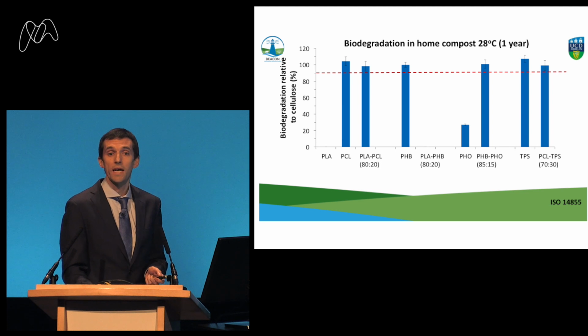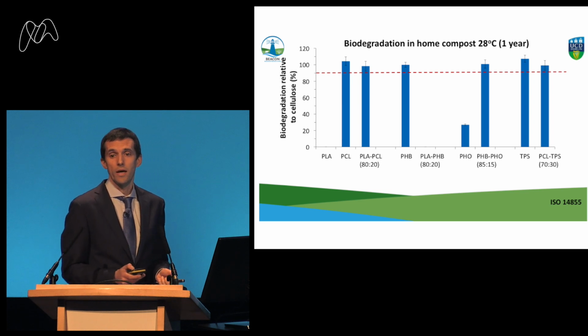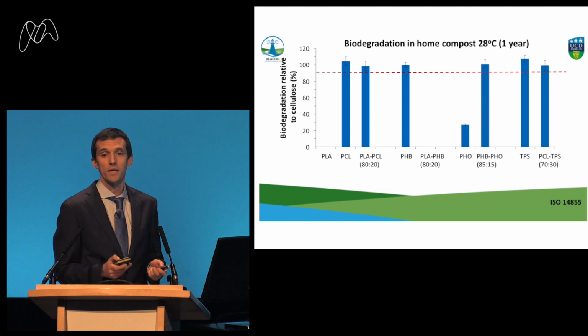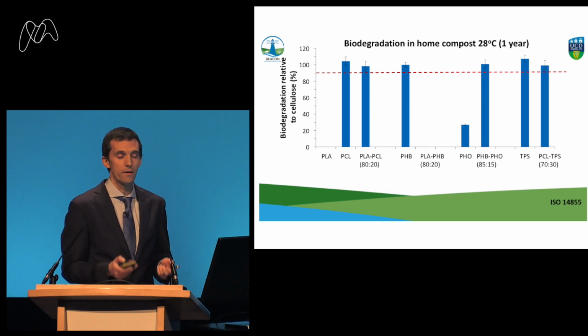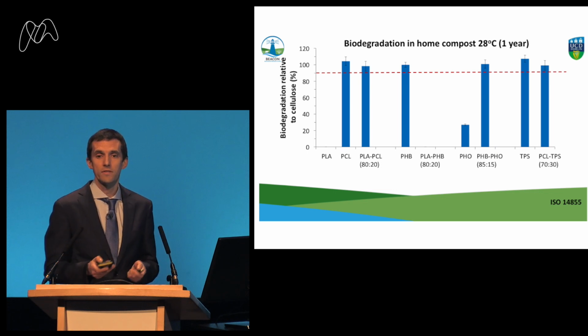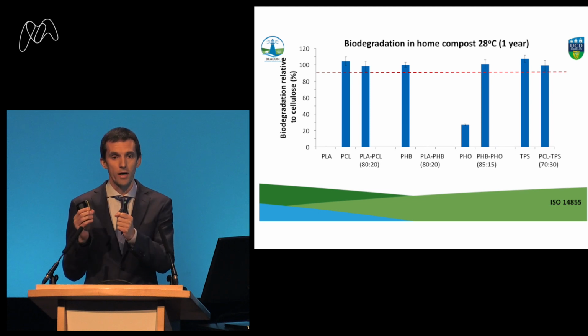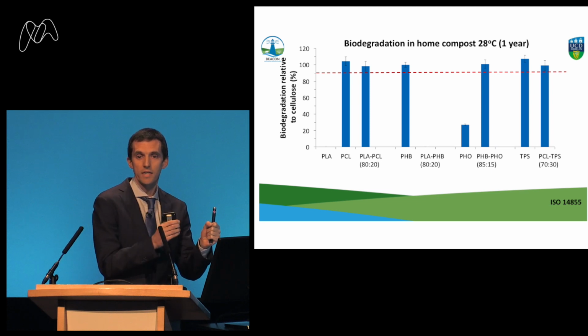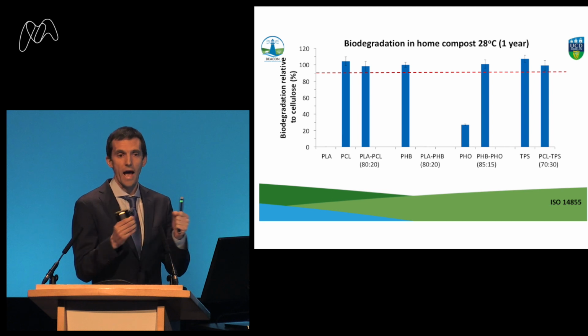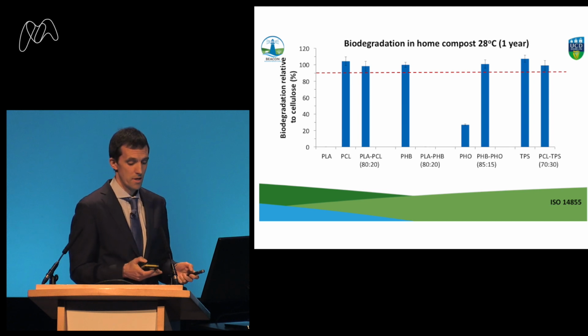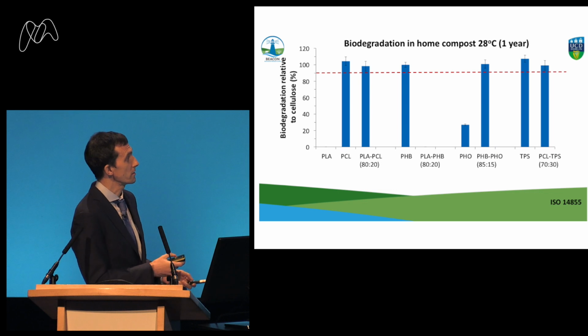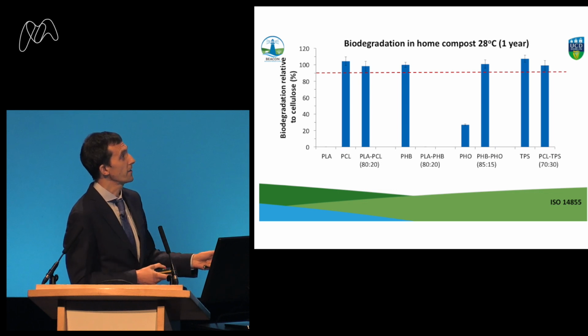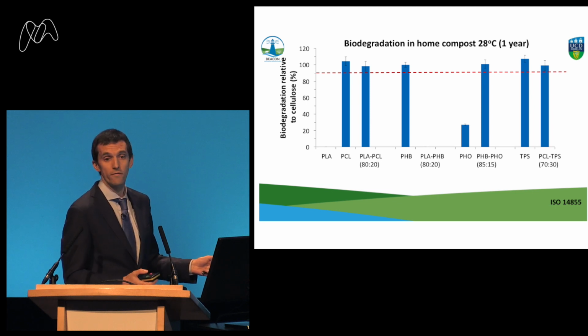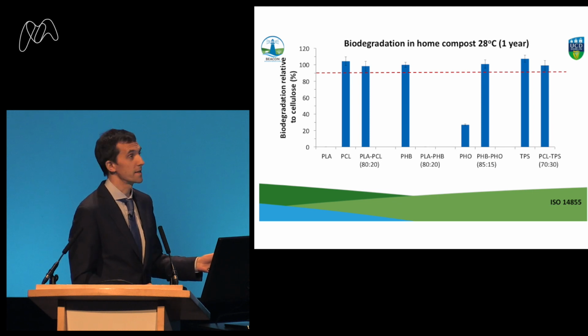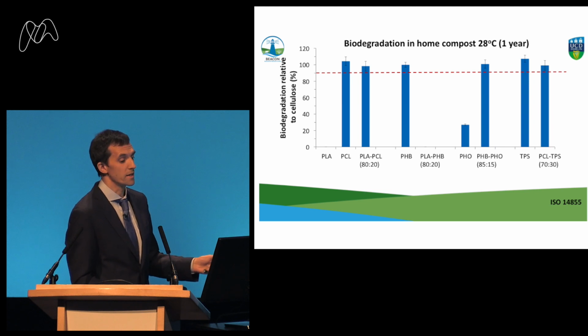We tried this also with PHO, which doesn't degrade very well in home compost. Can we mix it with PHB, which we know is home compostable, and only just a little? Because what PHO gives to PHB is flexibility. It's a rubber-like polymer. Blend that with PHB, and what you get is a strong and flexible polymer that could be used for packaging. And what we find is it then becomes home compostable. And again, for TPS and PCL, which are both home compostable, we were looking for antagonism, just in case there was some antagonistic effect, but they actually both degrade as well.